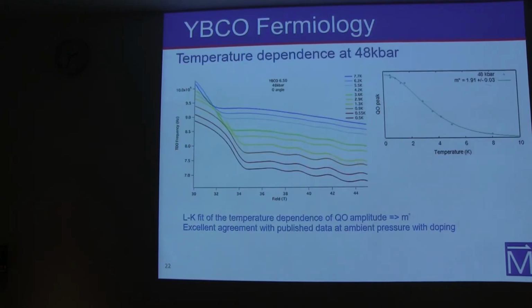So what we do for all of those pressures is actually a temperature dependence study to get an effective mass. So we do that for all the pressures. And this is one typical example that we did in Tallahassee, 45 Tesla, and at about 48 kilobar. So this is for one pressure. Here I show the TDR frequency as a function of field for increasing temperatures. And we see that for increasing temperatures, the quantum oscillation amplitude decreases and dies basically by 7 or 8 Kelvin.